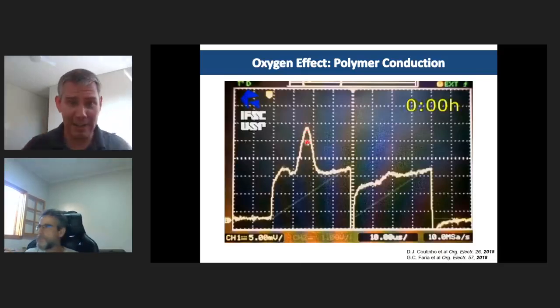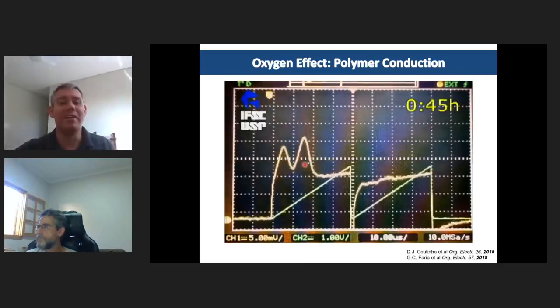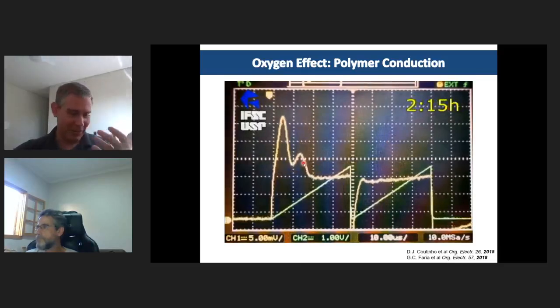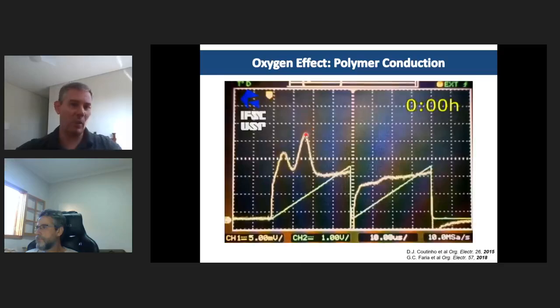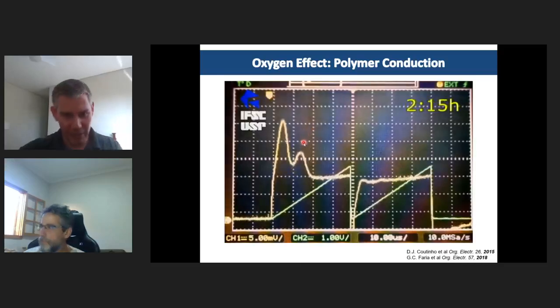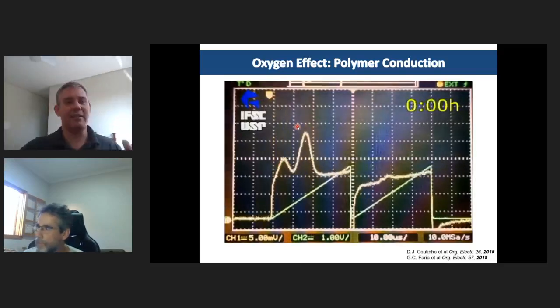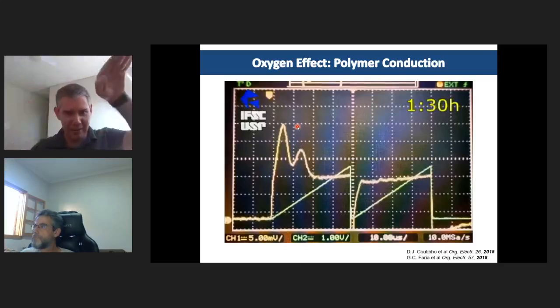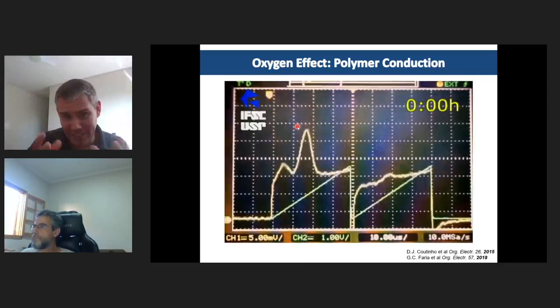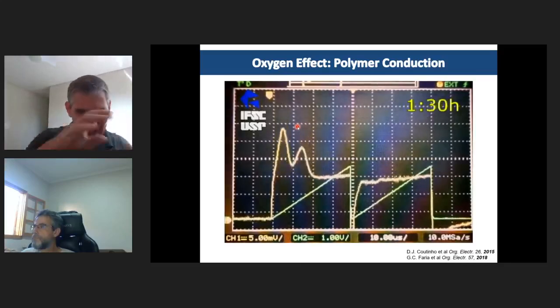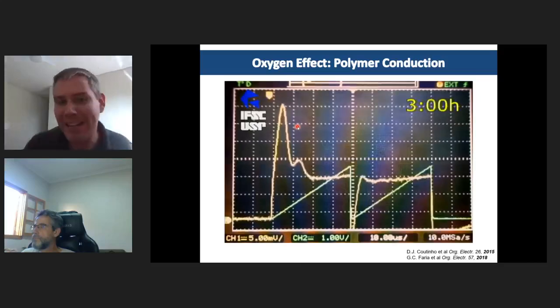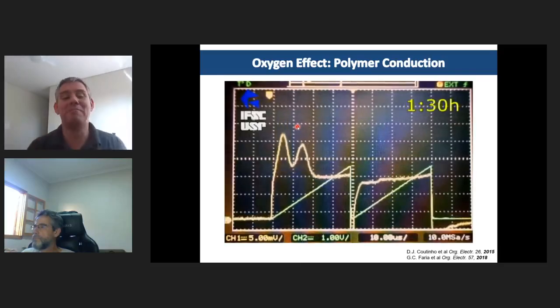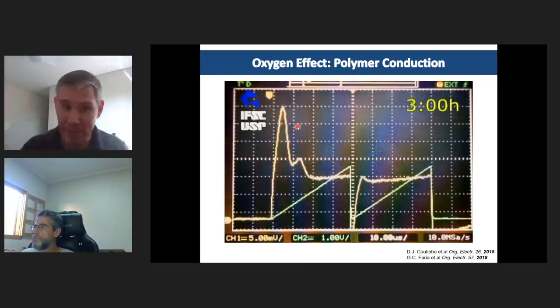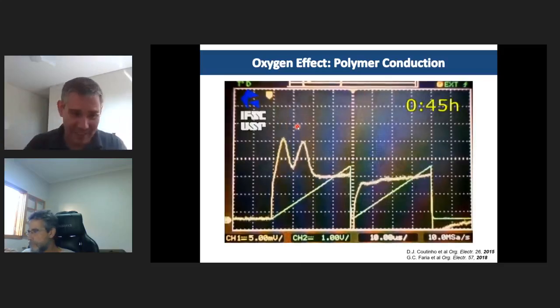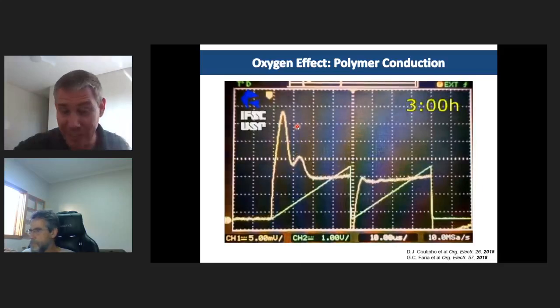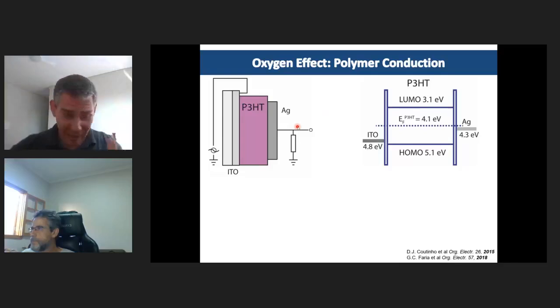So let's expose the device and see what happened. And this is actually in the film here. As you start exposing the device, there is something very interesting happening. The peak that was originally there for the unexposed device starts diminishing, and another one in the beginning of the ramp starts increasing. And you see that the rates at which they appear or disappear are mostly the same, suggesting that creating the new peak is actually diminishing or destroying the other peak. So we were very confused about this measurement, and we repeated it, we exchanged the batch of material we thought was contaminated, etc., etc. But everything was always behaving like this.